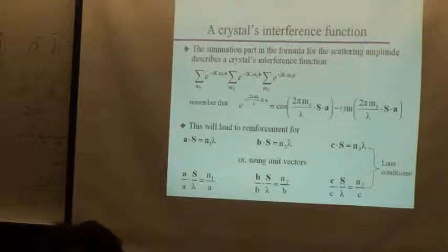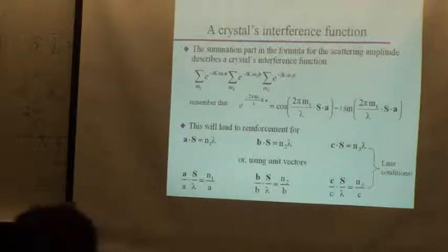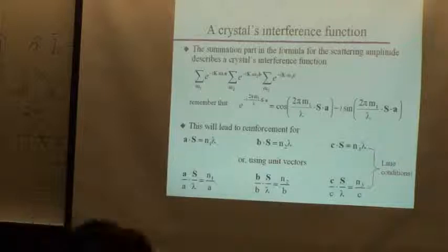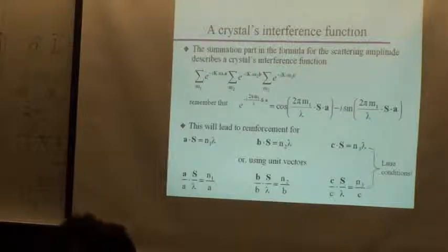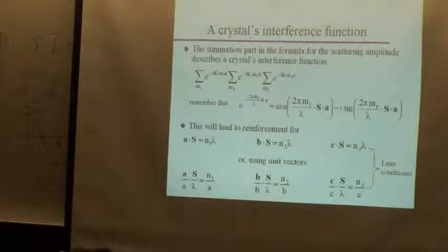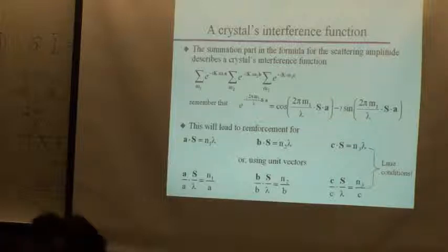Really happens. So, if we look back at these, this is actually our good old Laue conditions back that we talked about in the last lecture, okay? Path differences in 3 directions have to be an integer times lambda. Remember that one? Now, this time we wrote it as vectors still, right? So, this is where things allow us to actually gain some knowledge about reciprocal space.